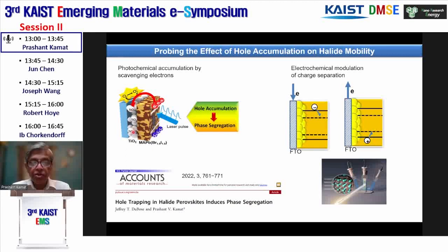Whereas if you have an electron transport layer like TiO2, the electrons move quickly into TiO2, and if you have oxygen, it can take away these electrons, leaving excess holes in the perovskite. So that is the strategy, and we wanted to see whether that can induce segregation. In the other case, we use electrochemical modulation. That means we can either pull out the electron or inject holes into this system and see what kind of changes we see. Again, this is a totally different way to inject holes electrochemically to prove our point.